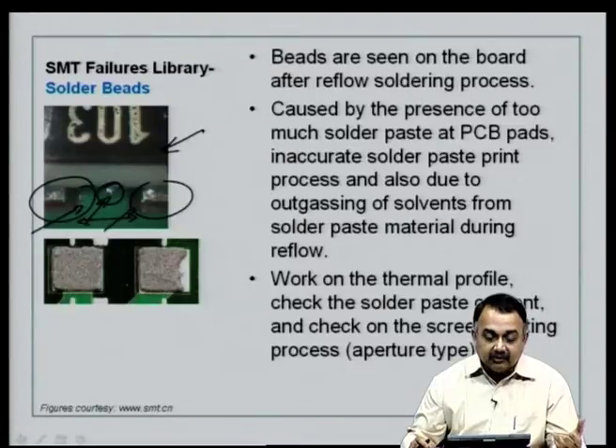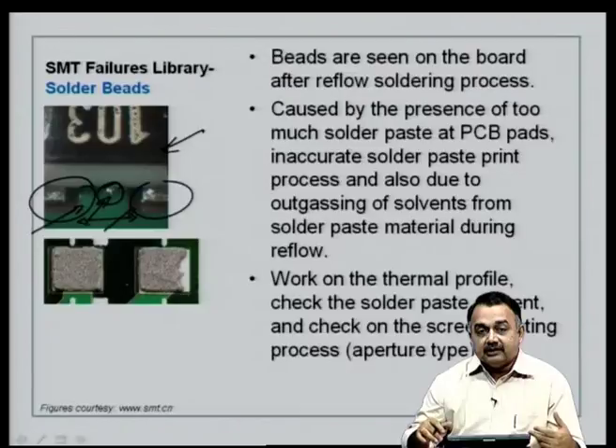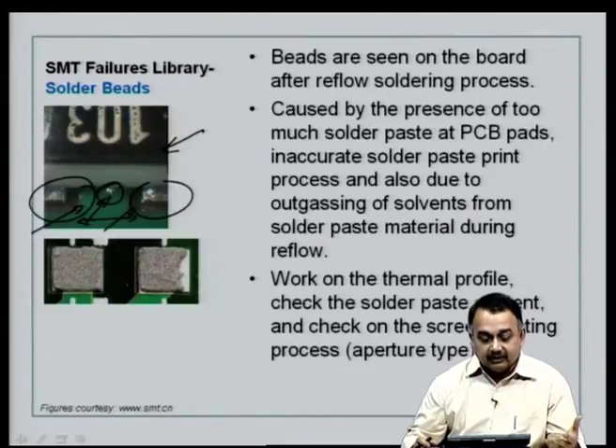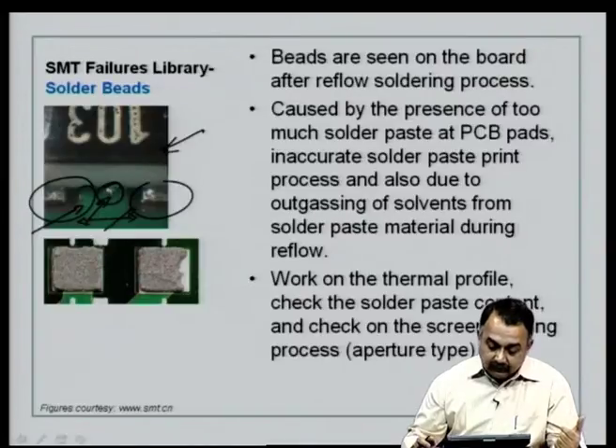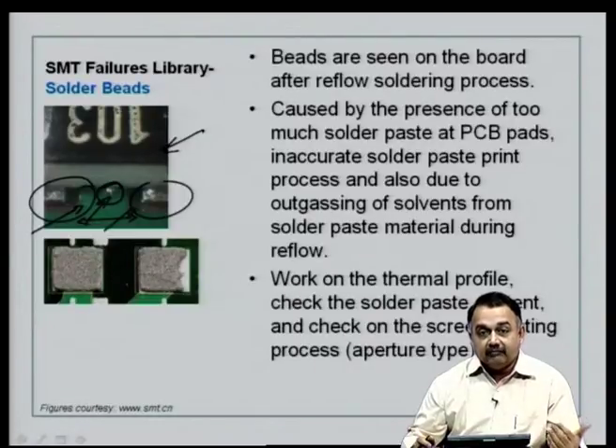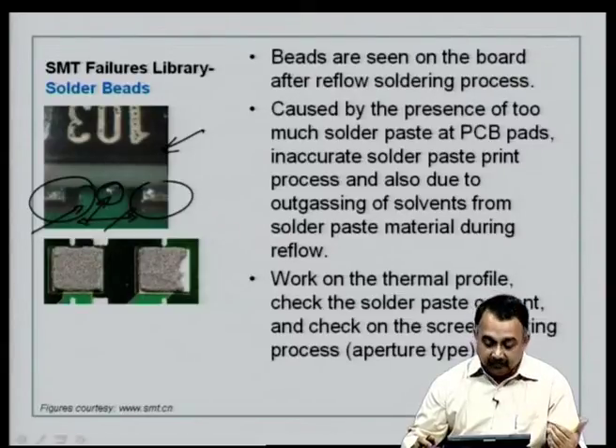So, beads are seen on the board after reflow process. How has this happened? The solvents in the solder paste have boiled or evaporated, because you have set a thermal profile which is absolutely wrong. You have done a very fast preheating and then it has outgassed. All the material has sputtered, and during the sputtering process the solder bead has been thrown out close to the package or under the package or close to a copper pad. Okay. So, outgassing of solvents due to poor thermal profile from the solder paste material during reflow is one of the main reasons for solder bead formation.